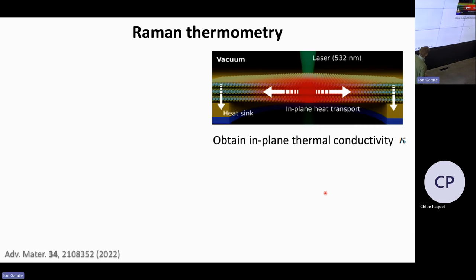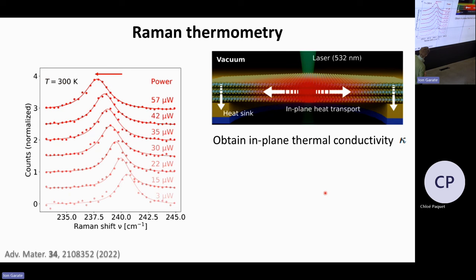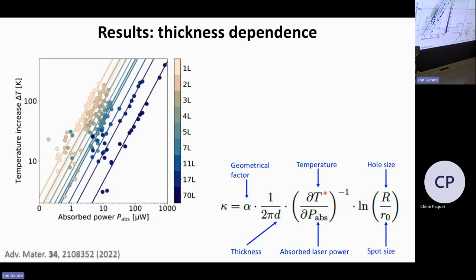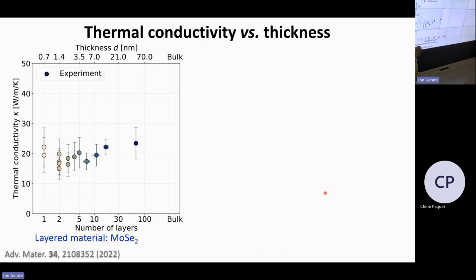And then we're going to look at how heat is spreading. So phonon heat. We have a technique for that called Raman thermometry. I think I can skip the details of that. You basically look at the shift of a Raman peak, which is correlated with your temperature. And then through a model, you can get the thermal conductivity. So let's jump to those results.